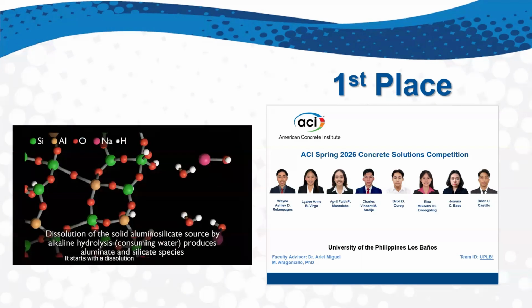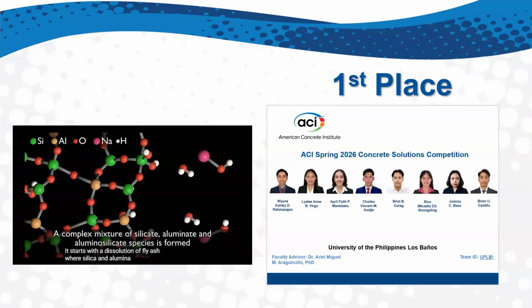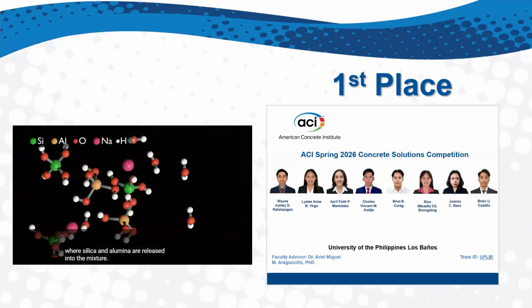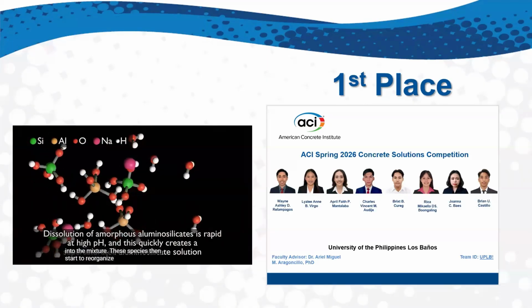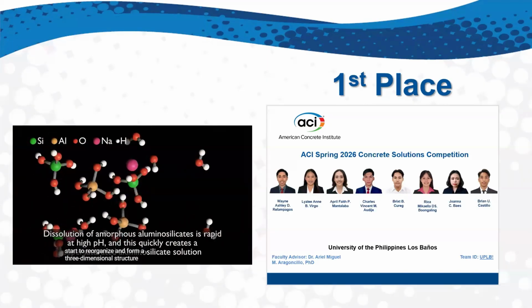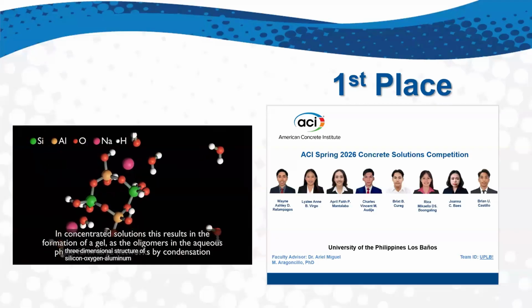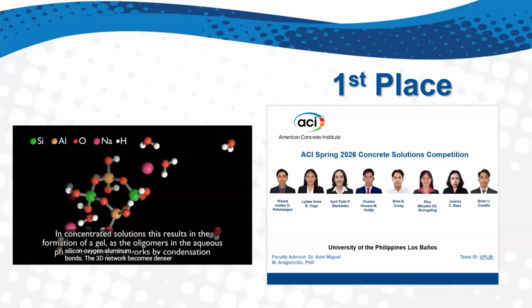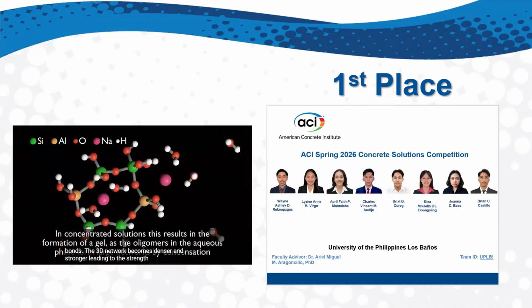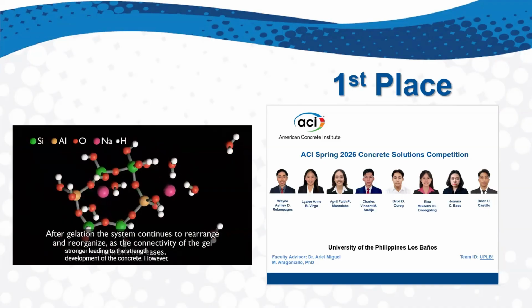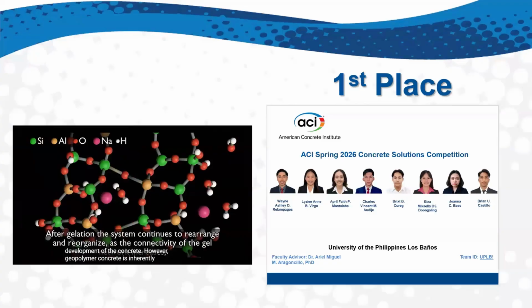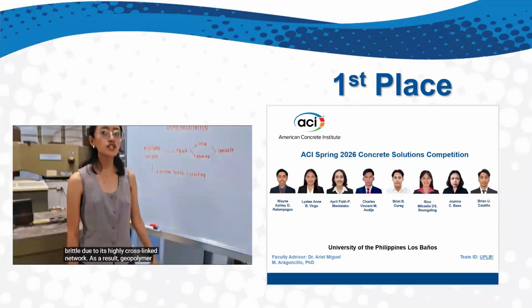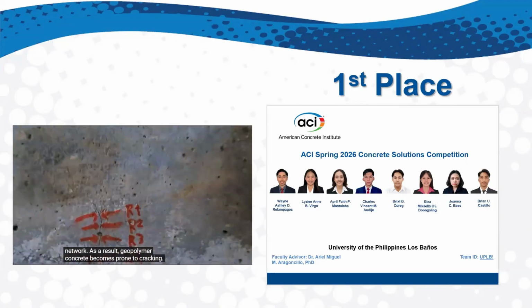It starts with the dissolution of fly ash, where silica and alumina are released into the mixture. These species then start to reorganize and form a three-dimensional structure of silicon-oxygen-aluminum bonds. The 3D network becomes denser and stronger, leading to the strength development of the concrete. However, geopolymer concrete is inherently brittle due to its highly cross-linked network. As a result, geopolymer concrete becomes prone to cracking.